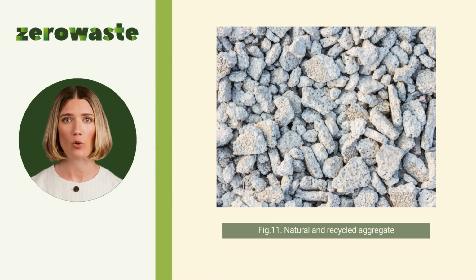Shrinkage, creep, and durability also differ in recycled concrete. Shrinkage may be 20 to 50% higher with full replacement of coarse aggregates, and up to 70 to 100% higher when both coarse and fine aggregates are replaced. Creep increases by 30 to 60% depending on the level of substitution. In terms of durability, replacing up to 30% of natural aggregate shows no loss of frost resistance, water absorption, or permeability. Beyond this level, water absorption increases significantly, carbonation depth rises, and resistance to chloride penetration decreases. After 25 to 50 freeze-thaw cycles, compressive strength decreases by about 25%, and mass decreases by around 5%, regardless of the replacement percentage.